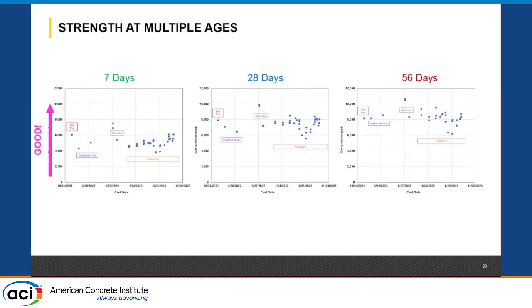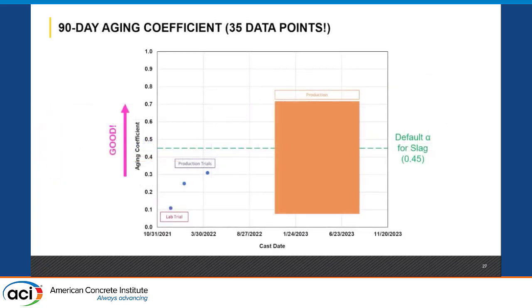We never had non-compliant strength. Strength wasn't an issue. It was just the resistivity. This is a very valuable slide because this is a bunch of alphas tracked with time. Each of these data points is 3 resistivities up to 90 days. Again, I showed that early on we were not great. It was kind of like in the 0.3 range.